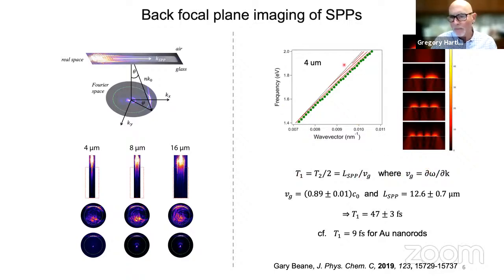So this is an example for a nanostripe that had a width of 4 microns. The green dots are our experiments. For that size structure, there are actually a bunch of different leaky modes. They have different orders. So these are plots of what those modes look like generated in COMSOL. And so these red lines here are the dispersion curves for all these different leaky modes, right? So you can see a bunch of them. We mainly seem to see this lowest order mode. Maybe it has something to do with the overlap of the laser with the form of the modes.